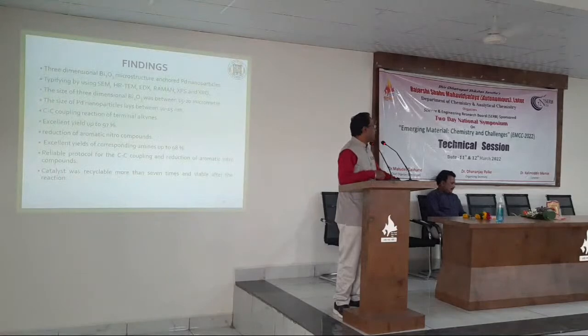In which it was reported, this was the finding where up to 98% yield is reported by using this method, and the size was found to be around 10 to 15 nanometers.